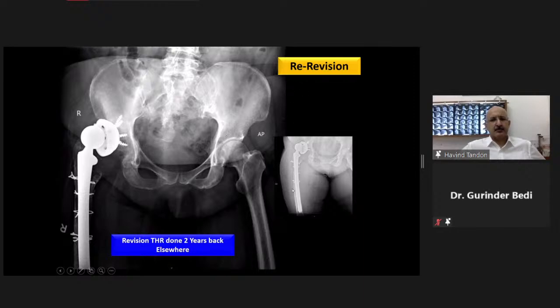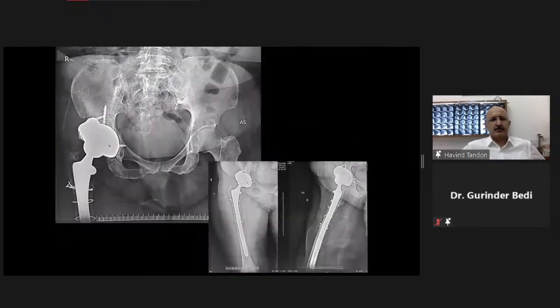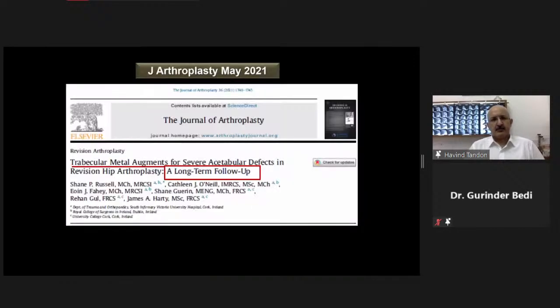The patient was quite bulky, a heavy lady, but the stem was very well fixed. So we went prepared to change the stem even if required. But the stem we found was very well fixed, and we could do well with augments and a tantalum shell with good fixation. And this lady is also doing well in follow-up. So trabecular metal augments at 15 years follow-up, if you see, the results are very good, excellent and very exciting.